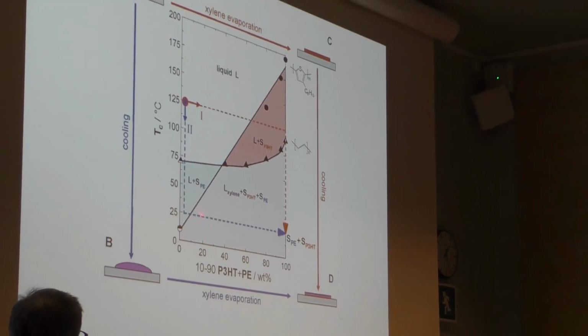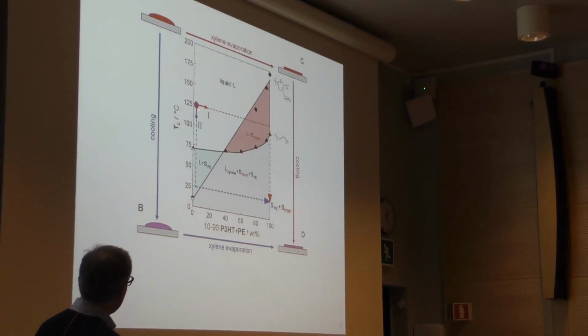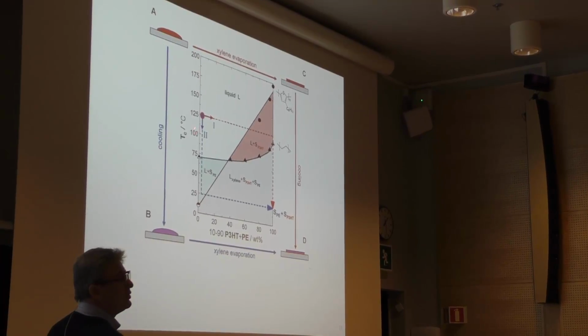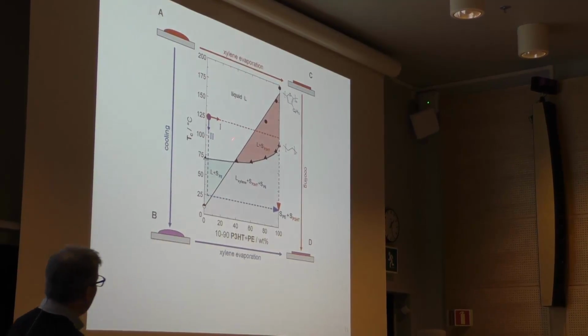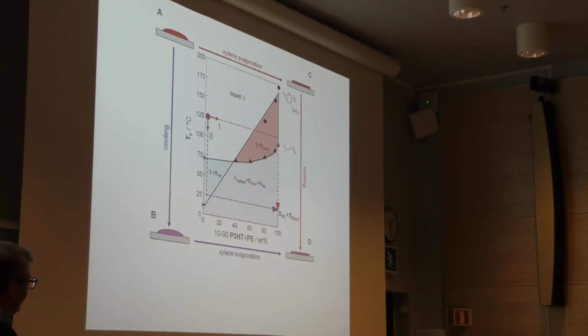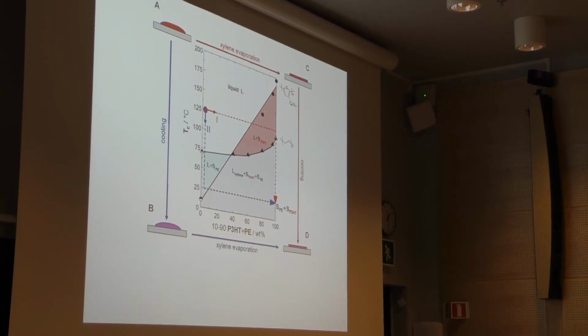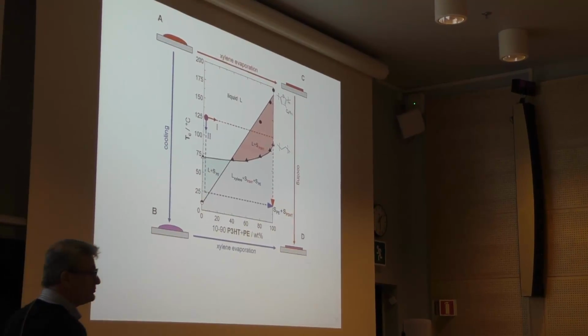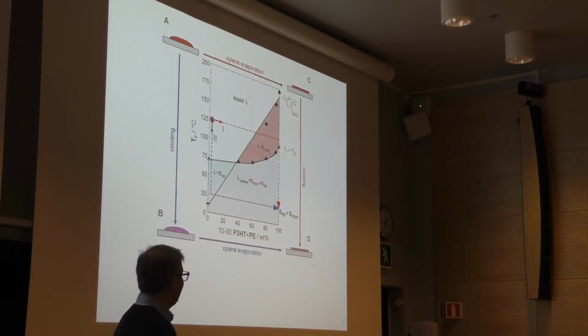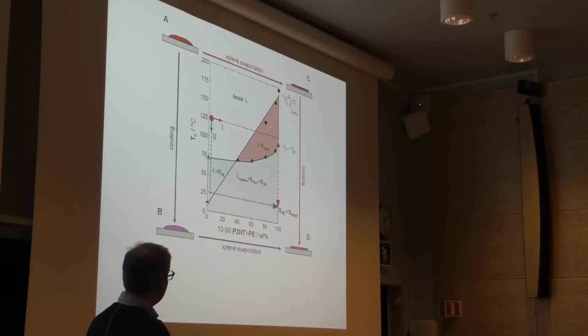And an even more striking example of this was constituted in this case, where we had polyhexyl thiophene mixed with polyethylene in xylene. And when we had this mixture starting up here with a diluted solution at 125 degrees, we wanted to go down here, right? We wanted to have all the solvent evaporated and to go back to room temperature. So there turned out, well, there are 2 obvious ways to do this, right? You can consider that you either first let the solvent evaporate and then you cool down, or you just cool it down and then you let the solvent evaporate.